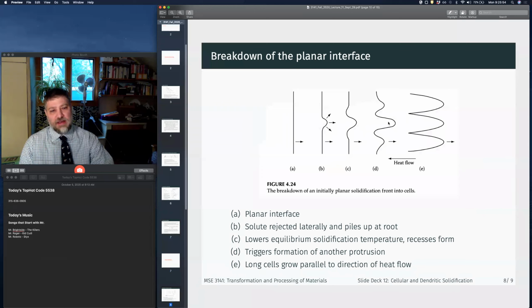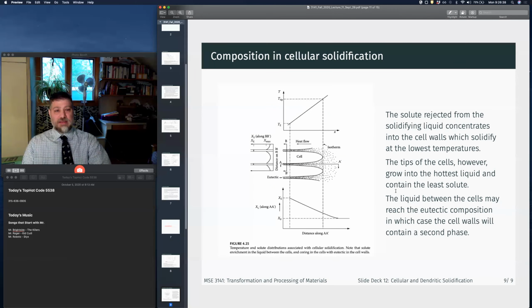And we actually form this oscillating interfacial structure that grows into these long fingers. The important thing is that these long fingers are going to grow parallel to the direction of heat flow. We form a protrusion, and we form recesses next to the protrusion. These form with a characteristic wavelength and spacing, and there's a lot of really cool theory for predicting this wavelength and spacing that we're glossing over here to get the main ideas. Okay.